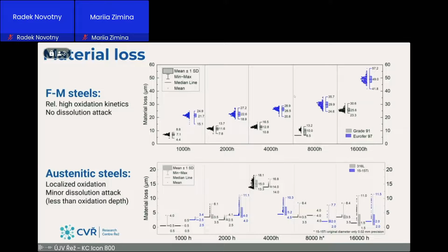There is a comparison of ferritic steels. We also tested the Eurofer, I didn't mention, just for our interest, and there is stainless steel. You can see here that austenitic steel has virtually no corrosion damage except this 4,000 hour specimen. Ferritic martensitic steel exhibits some, let's say, uniform oxidation that gradually increased in time, with the exception of this 8,000 hour grade 91 specimen. You can notice here that the corrosion of ferritic steels is much higher, the material loss.